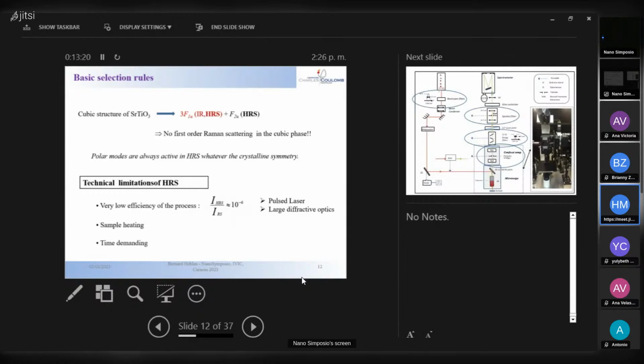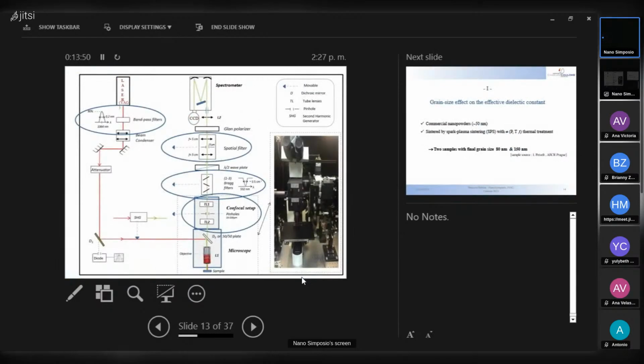But there are limitations in hyper-Raman scattering. For example, the process is 1 million times weaker than in Raman. So if you have to spend 1 minute to make a Raman spectrum, you have to spend years to make a hyper-Raman spectrum. So one idea is to use a high power laser and high diffractive optics to compensate for this lack of intensity. And so 15 years ago, we constructed a hyper-Raman setup in Montpellier. And just to give you some details, you use a pulsed YAG laser, because then you have very high power pulses at your disposal to make your scattering.